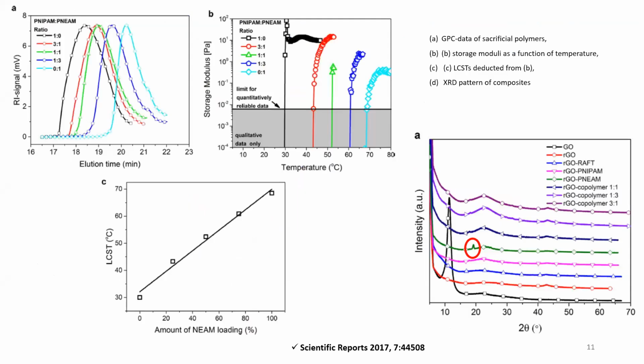So here are some results. At the top left, you can see that the molecular weight of the polymer reduced by increasing the N-ethyl acrylamide ratio, because it is more hydrophilic and the sheets are hydrophobic. So this repulsion is the reason for this. We also saw a linear relation between LCST and N-ethyl acrylamide loading. And with these composites, we could tune the LCST from 30 degrees to 80.